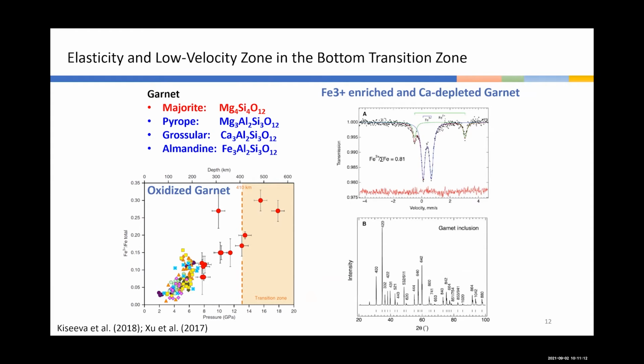And especially from the petrological observations in most recent years, we see that there is a great increase in the ferric iron concentration with depth. So in the transition zone, we can see the Fe3+ content is pretty high.